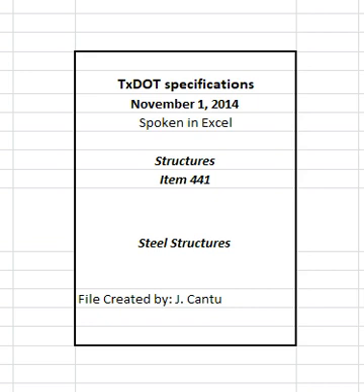3.8.1 Shop painting. Perform shop painting of bridge members as required in DMS 8104, Paint, Shop Application for Steel Bridge Members. Grind corners on new steel items to be painted, except for the coatings on box and tub girder interiors, that are sharp or form essentially 90 degree angles to an approximately 1/16 inch flat surface before blast cleaning.